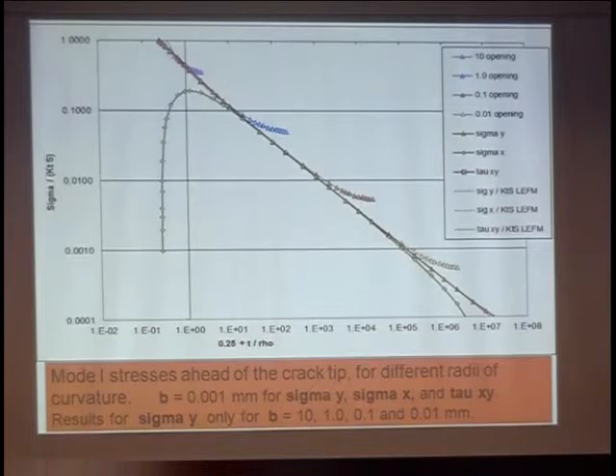Well, we didn't have to do that because we wanted to put on the static compression and therefore it had to be an axial crack. So we didn't choose to do that. But I'm sure if we did that, we would get the same result, unless, of course, we could make a very sharp crack. The example where you see that working well is in my picture of the normal cyclic fatigue torsion curve at the beginning. That will give you either circumferential cracks or axial cracks, you get both.